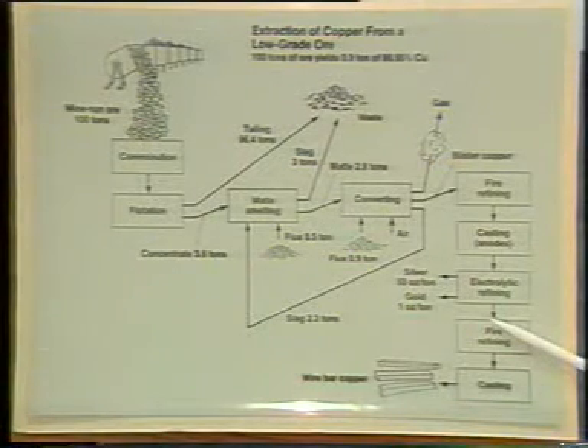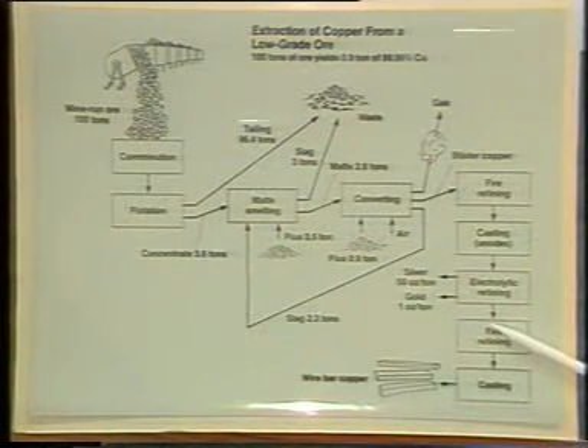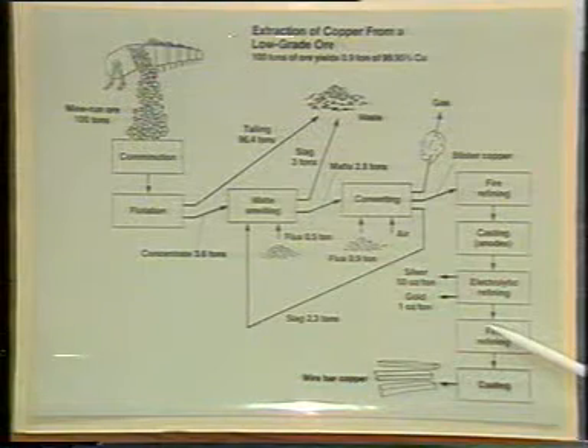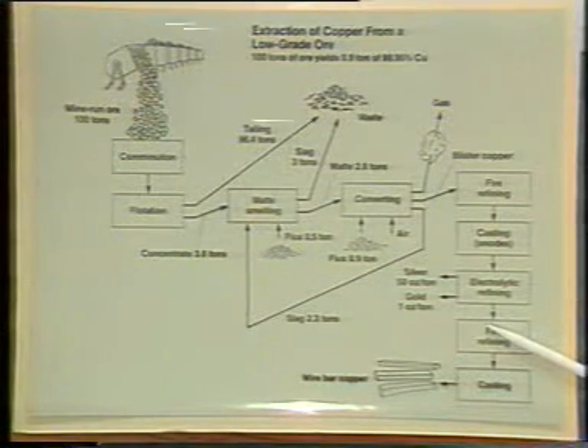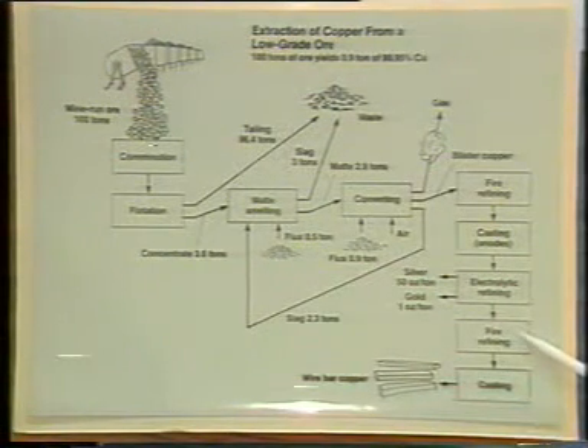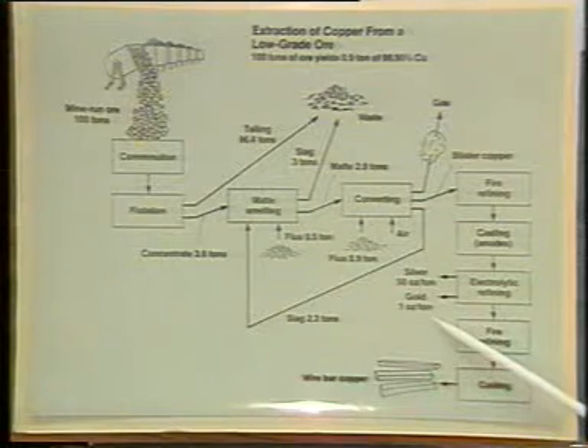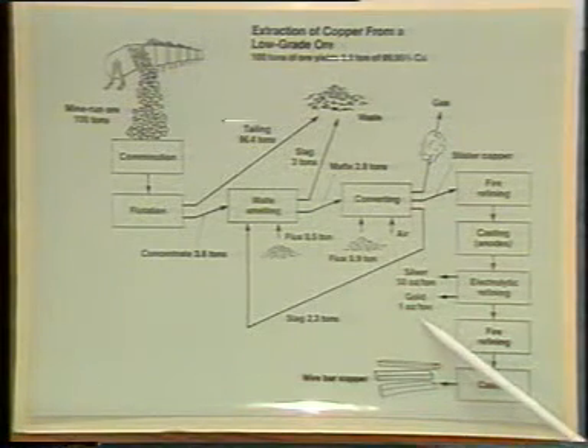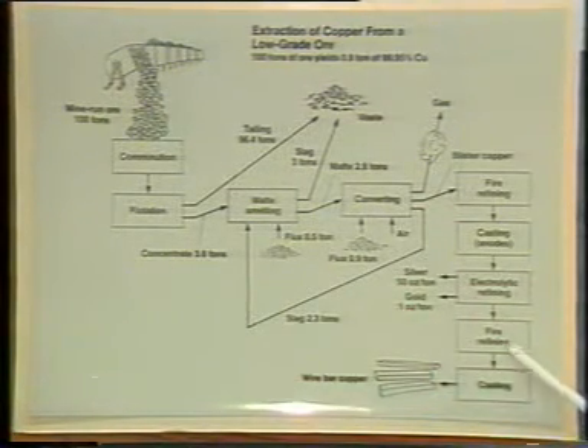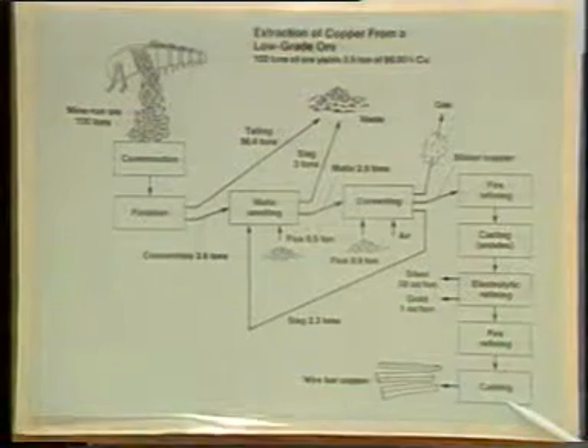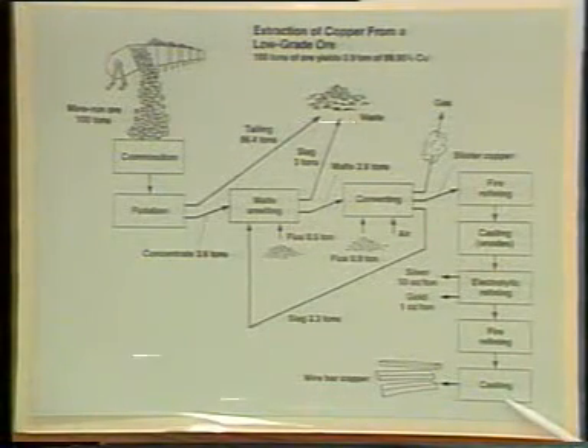But when they're through with this, all they're really going to have now is a bumpy looking plate about the size I am, about 5 feet tall and about 3 feet wide. And that particular material is going to be a bubbly, blistery looking material. It's going to have some hydrogen in it because we're also going to decompose the electrolyte a little bit and plate it with some hydrogen. And so we put it back in a casting house, melt it again, and cast it.